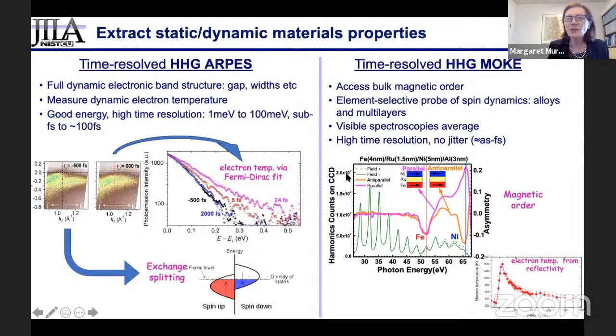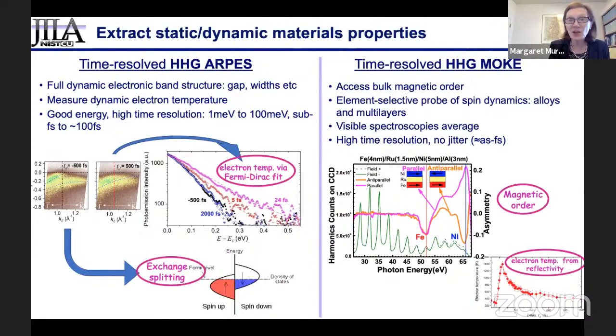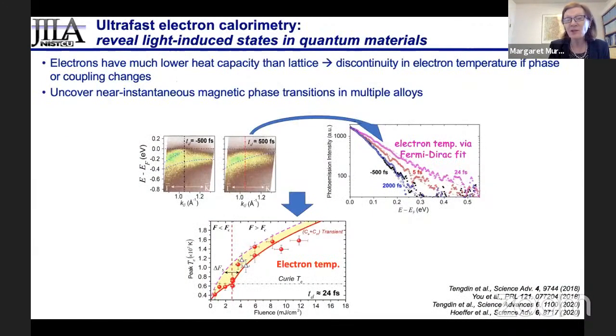It's because if you combine photoelectron spectroscopies with magneto-optic probes, you can actually look at the Fermi edge and fit that Fermi edge and extract the instantaneous electron temperature. You can also look at exchange splitting. And that allowed us to uncover something very unusual, that if you measure the electron temperature as it's being heated